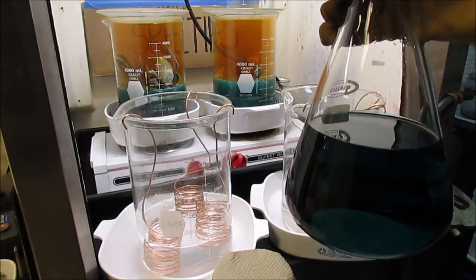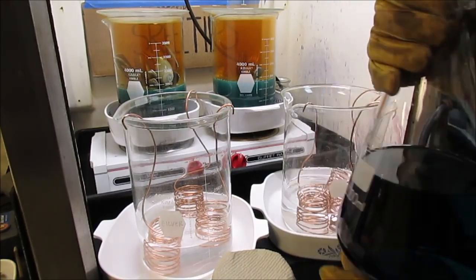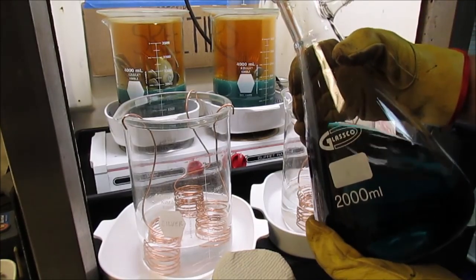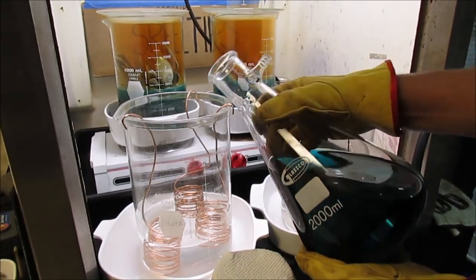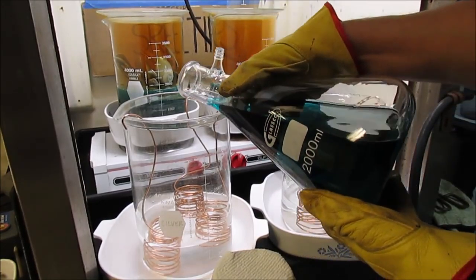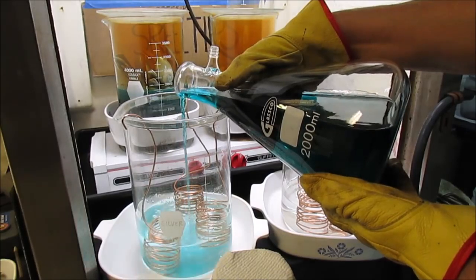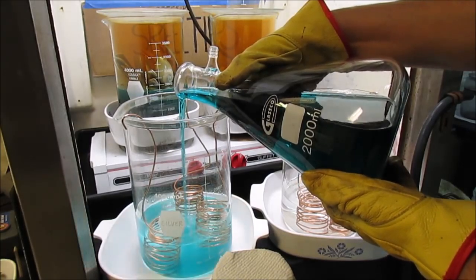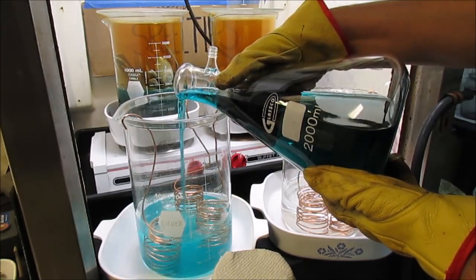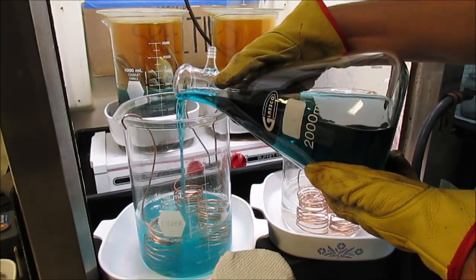Now I'm going to add some of the silver solution and start the reaction to cement the silver out of this solution using this copper wire. Just going to add it slowly. It should start immediately. You should start seeing some silver forming on those pieces of copper.